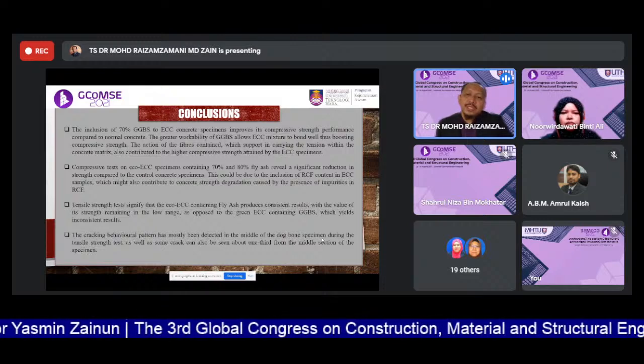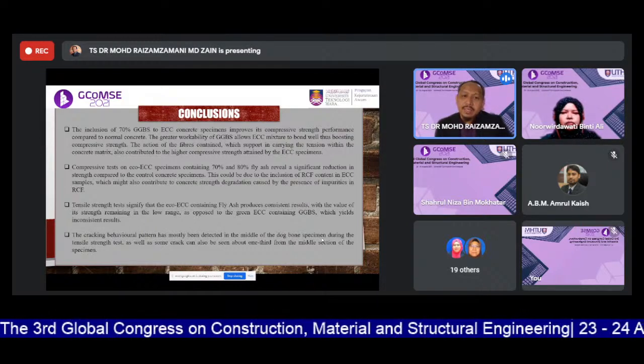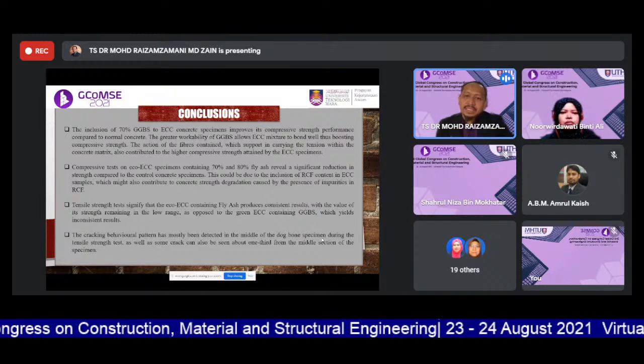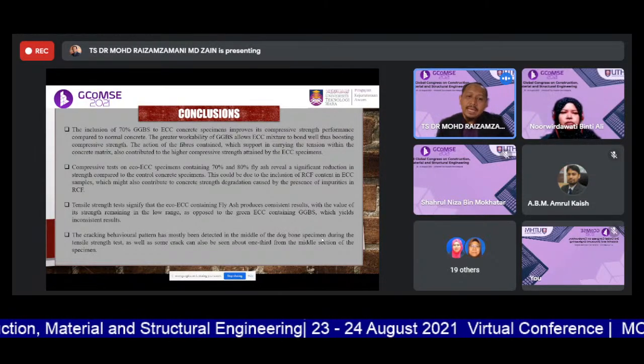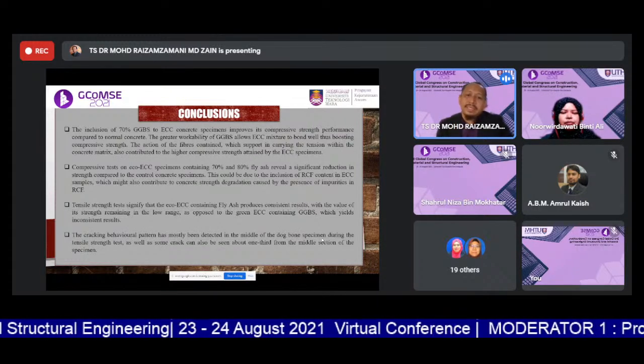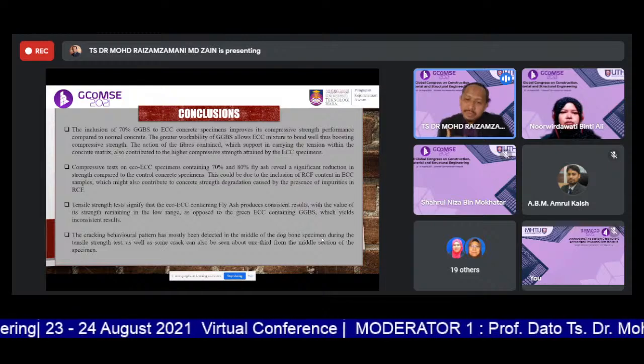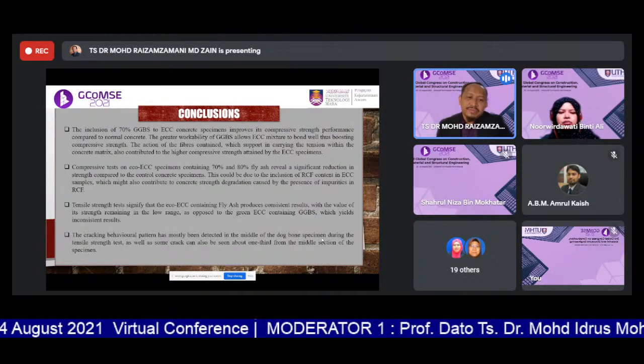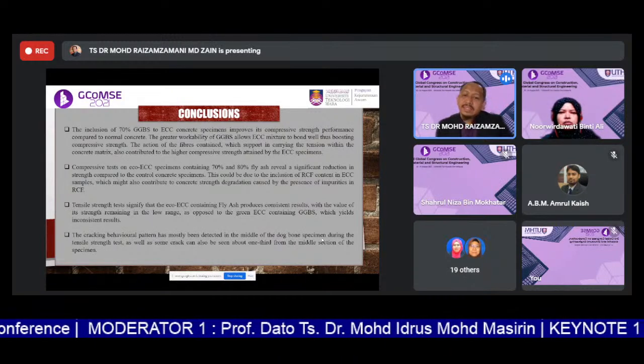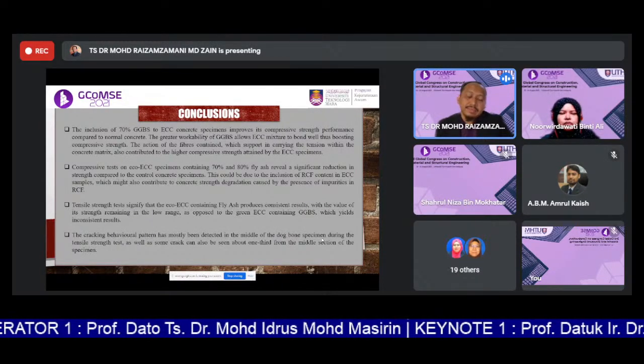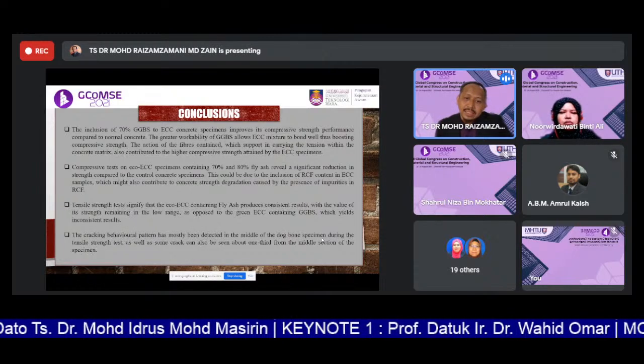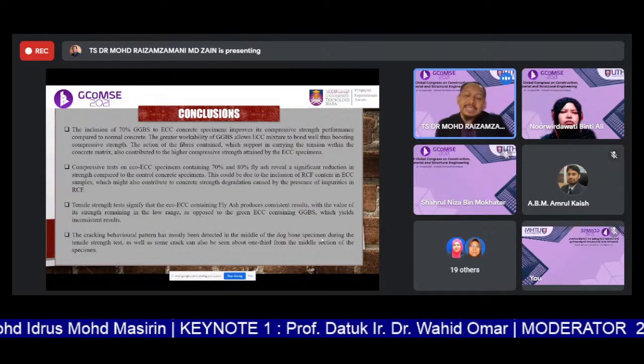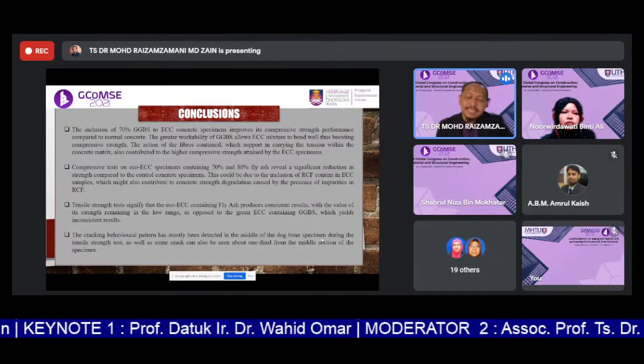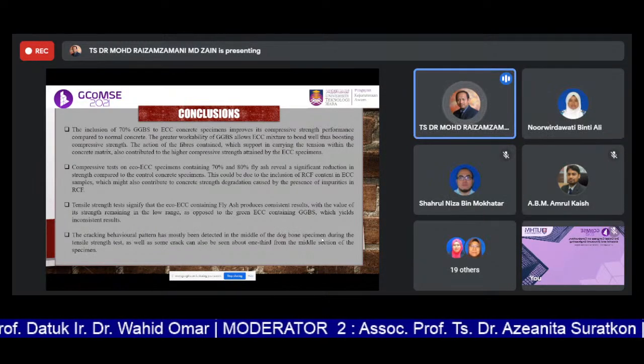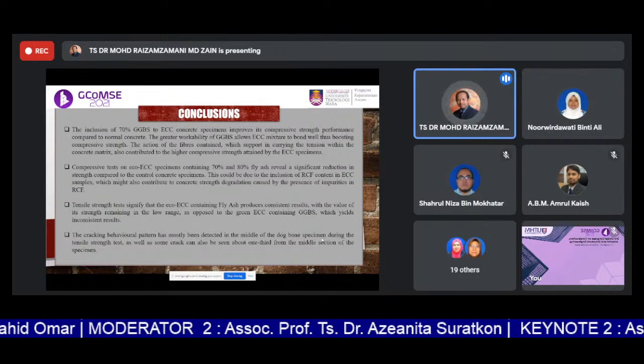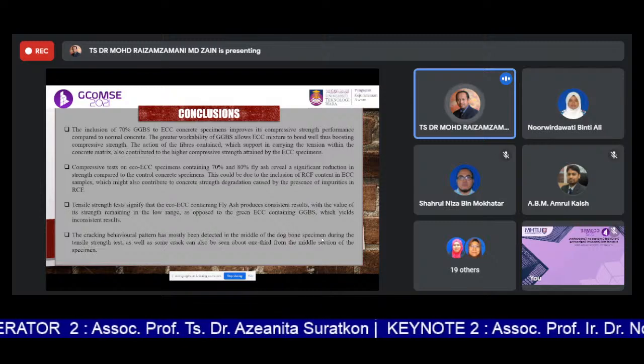This could be due to the inclusion of RCF content in the ECC sample, which might also contribute to the concrete strength degradation caused by the presence of impurities in RCF. And the tensile strength test signifies that the eco ECC containing fly ash produces a consistent result, with the values of its strength remaining in the low range, as opposed to the green ECC containing GGBS, which yields inconsistent results. The cracking behavioral patterns have mostly been detected, as I said before, in the middle of the dog bone specimen during the tensile strength test, as well as some cracks about 1/3 from the middle sections of the specimens.